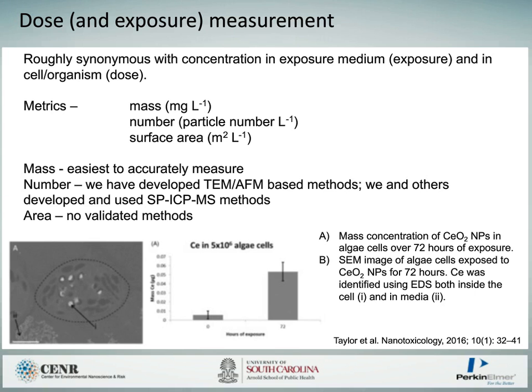So we're interested in, and the ICP-MS can help us with, understanding dose and exposure measurement. And roughly, we can say that the concentration in the exposure media is related to the exposure, and the concentration in the cell of the organism is related to the dose. And an interesting question that comes up in this area is how do we measure those concentrations? We can measure it by mass concentration, for instance, milligrams per liter. We can measure it as number concentration, particle number per liter, or surface area, meter squared per liter. And all of those can be important.